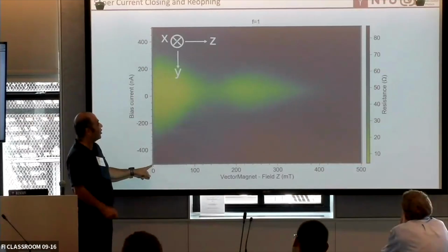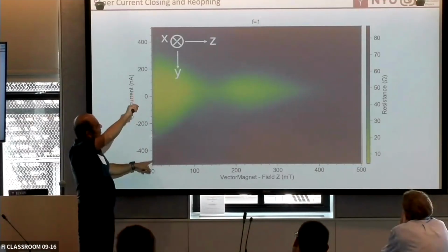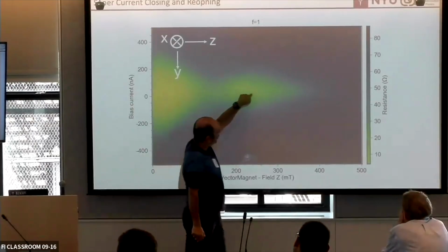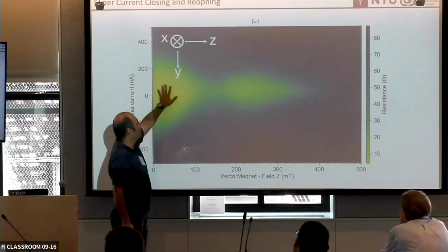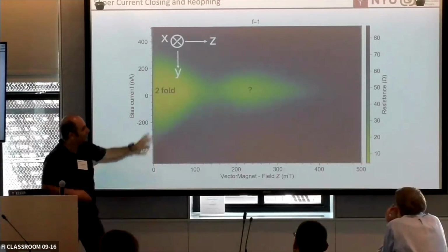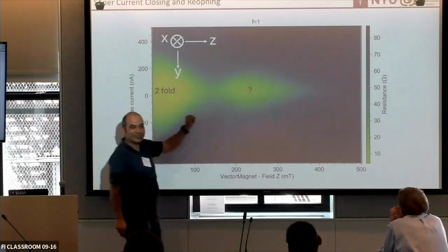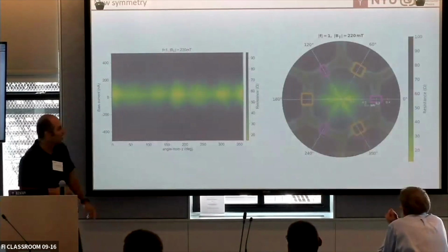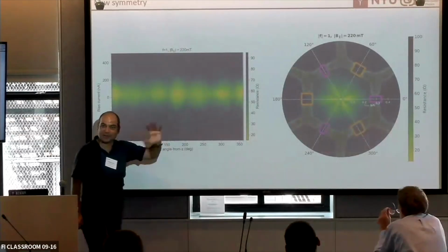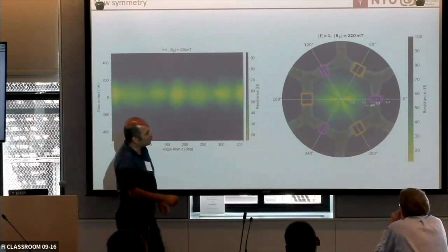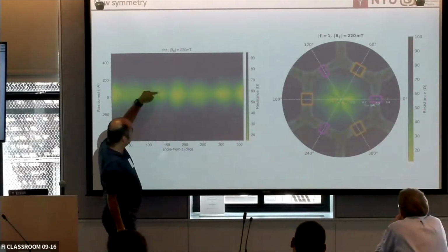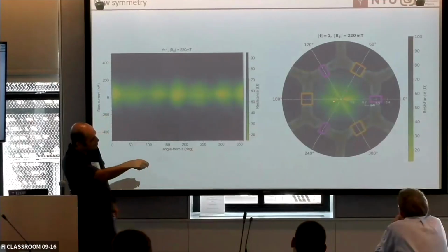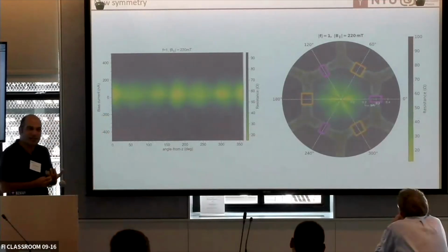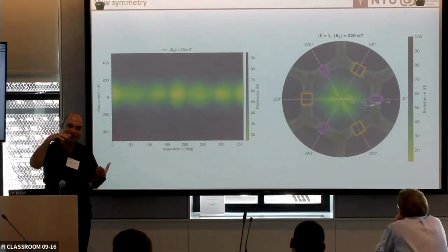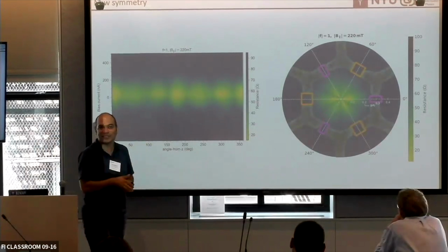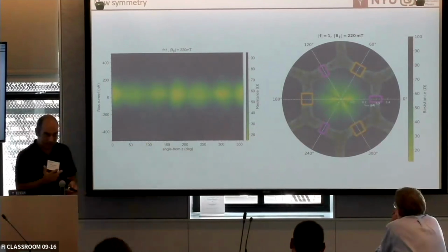So this is in-plane field at 0, sitting at filling factor 1. The supercurrent at 150 millitesla is gone. I go beyond that, and it comes back, right? I know here my symmetry was 2-fold. What is it here? The only difference, remember, is an in-plane field. When we go to 220 millitesla, after the reopening, you now see a 6-fold symmetry oscillation of supercurrent with the angle, and you can actually line it up with the junctions. It's a pretty big question for us: why should you have a closing and reopening, and why, across that closing and reopening, is the symmetry of the data changing? Is there a phase transition, or is this something trivial, which would be very strange?